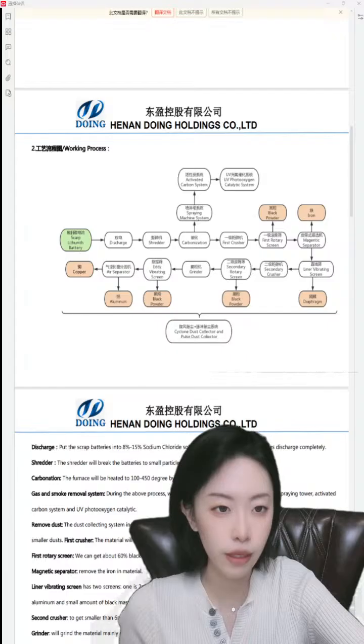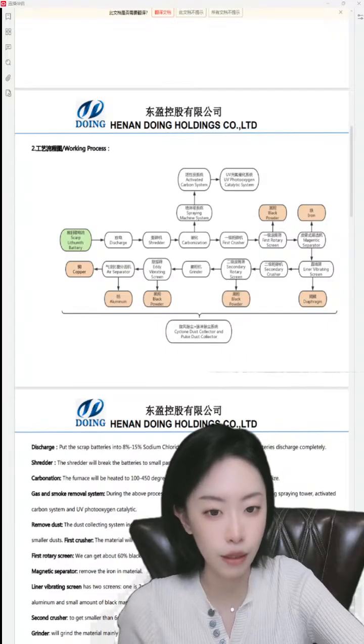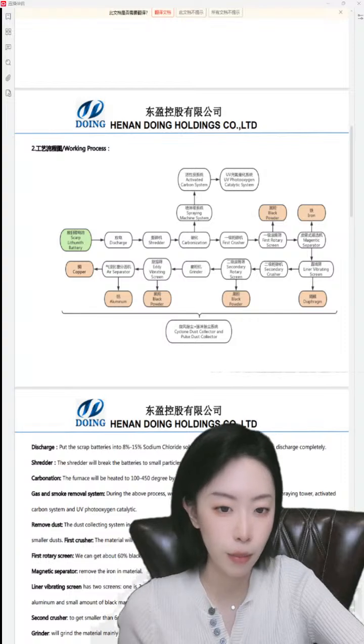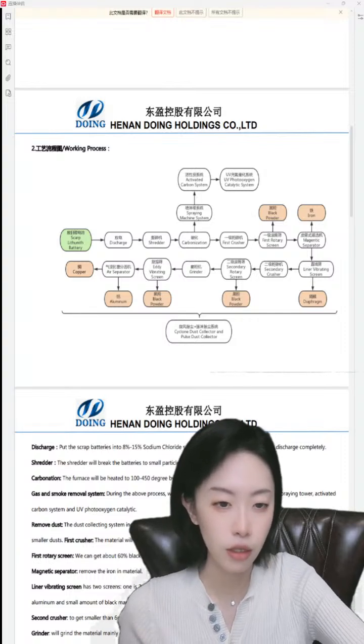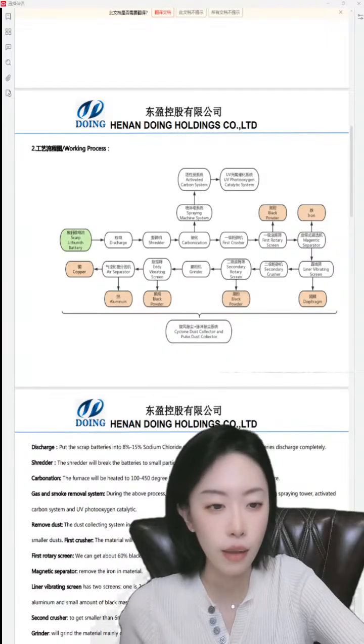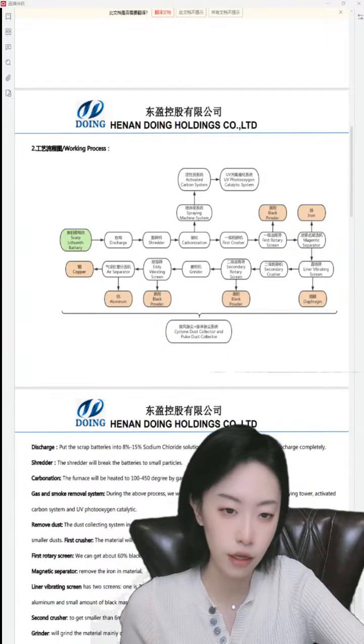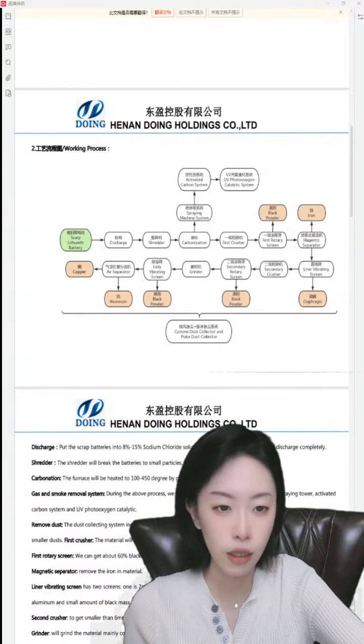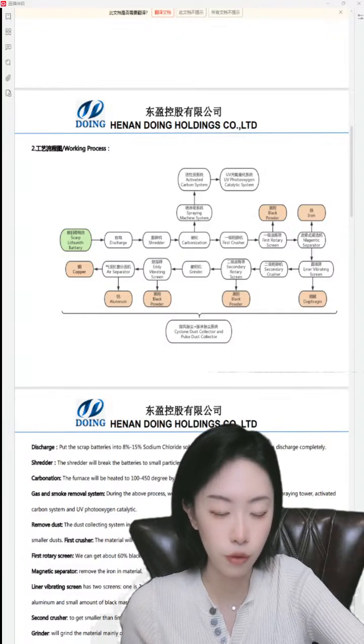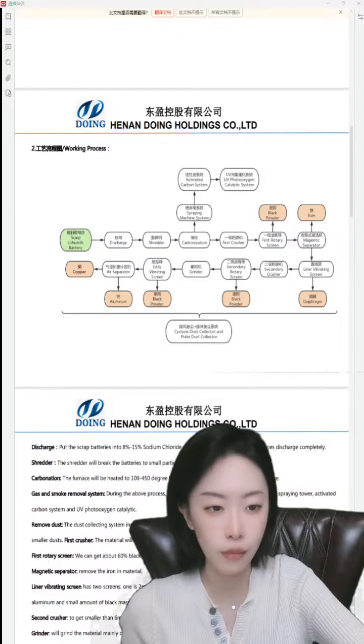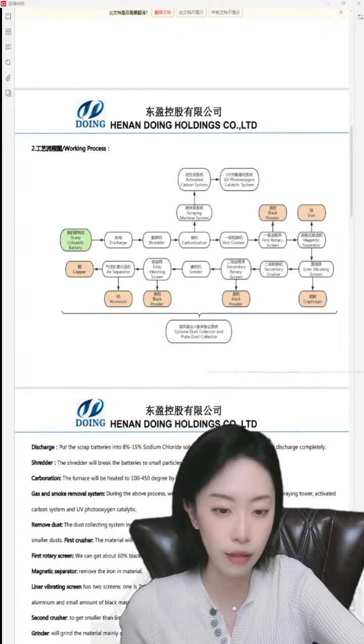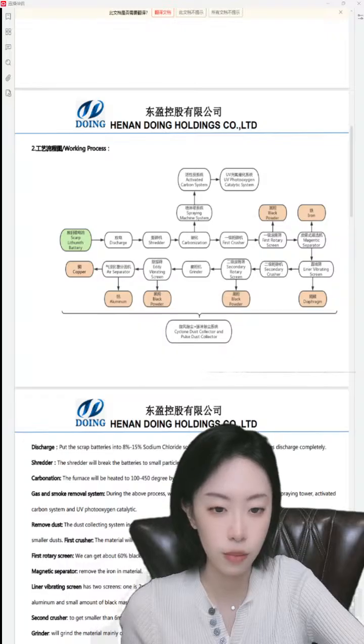Then we have the mixed copper and aluminium. So they will go into the air separator, also called the air gravity sorter machine. It utilizes the combined action of airflow and vibration friction on the material. The larger copper particles settle to the bottom, and the smaller aluminium particles are suspended on the surface of this layer just by the action of the airflow. And in this link, the recovery rate of the copper and aluminium is about 98%.